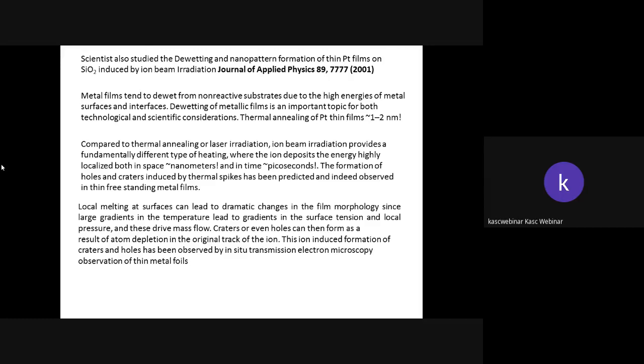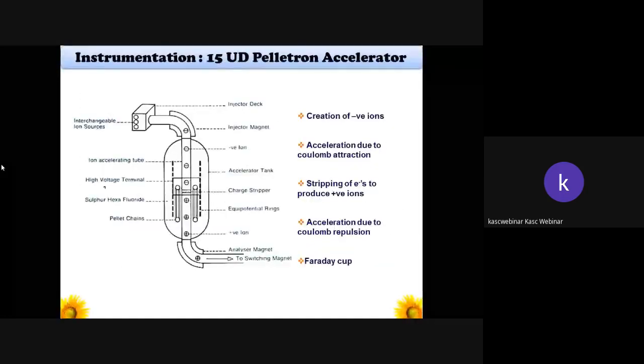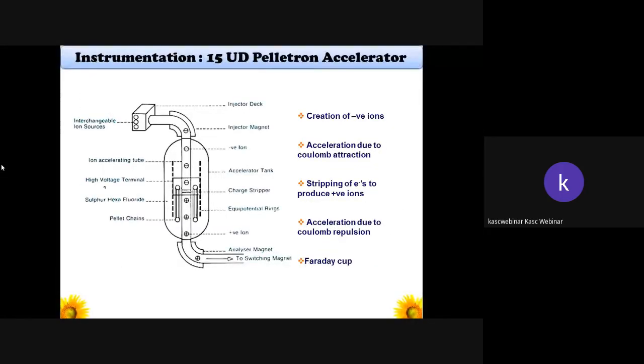The local melting at the surface can lead to dramatic changes in the thin film morphology, since a large gradient in temperature leads to a gradient in the surface tension and local pressure, and this drives a mass flow. The craters or even holes can then form as a result of atomic displacement in the region of the track of ions. This ion-induced formation of craters and holes has been observed by in situ transmission electron microscopy of thin metallic foils. Then what kind of instrument was utilized for such experiments?